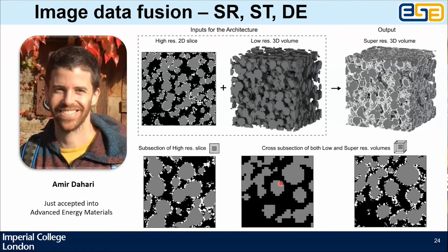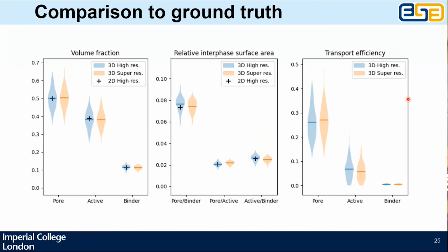So this exact region, once you've applied a GAN that's been trained on this high resolution data, will turn this thing into this thing here. And in our case, we had the ground truth available to us. So we'd sort of start with the high res, make the two different versions of the training data, and then we try and reconstruct this high resolution training set. And it gives you beautiful statistics.